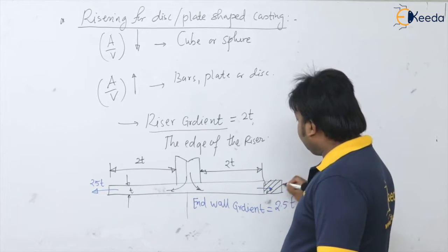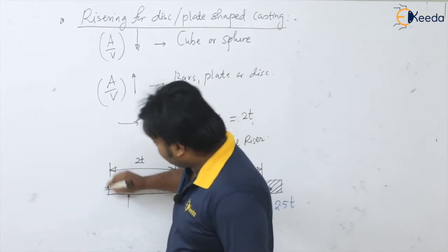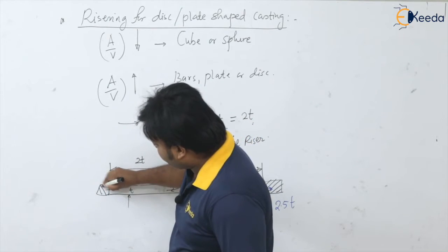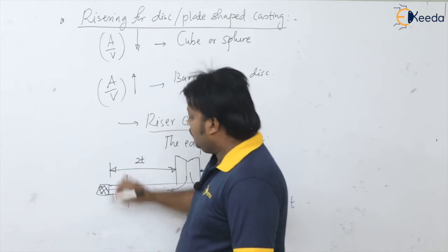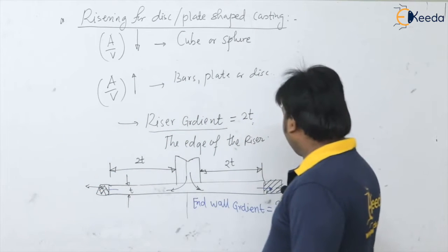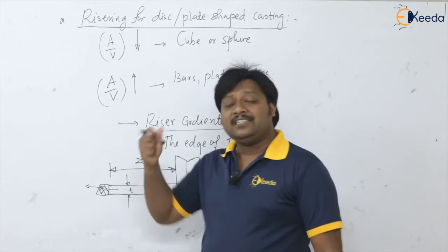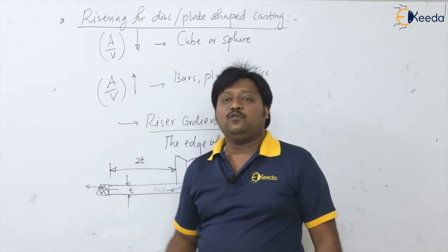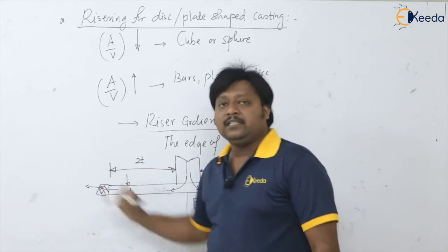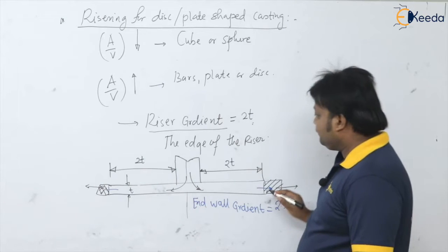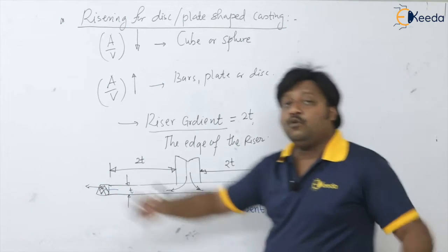Say this is the chill I am adding here. So again, you can go more distance because of this fast heat removal, so that you can go for more length for the riser feeding, isn't it? So definitely you will get more distance.